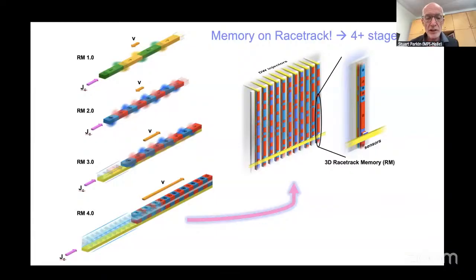And then in 2015, we demonstrated actually the most important development, that we could build a racetrack that itself has no net magnetization. So in this cartoon, in racetrack versions 1.0, 2.0, 3.0, these are ferromagnetic films, and these ferromagnetic films have domains, and the domains have magnetic poles, and these produce long-range magnetic dipole fields, as shown in the cartoons. And these fields cause interactions within one racetrack and between racetracks, which means it's very difficult to build dense racetrack memories. So what we demonstrated in this version 4.0 was essentially we built one racetrack on top of another one, where by design, the upper racetrack would have exactly the opposite magnetization to the lower racetrack.